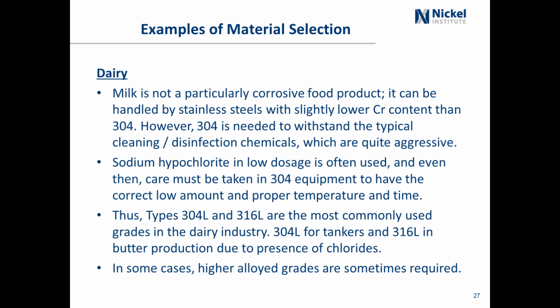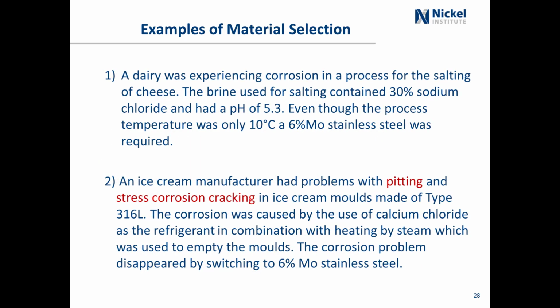Types 304 and 316L are the most commonly used grades in the dairy industry. Like in the case of tankers, 304L could be used, but 316L might be used in butter production because butter can have a lot of salt added to it. Here's some specific examples. A dairy was experiencing corrosion in a process for salting of cheese. The brine used to do the salting contained 30% sodium chloride and had a pH of about 5.3. Even though the temperature was low, only 10 degrees C, they needed a 6% molybdenum superaustenitic stainless steel to prevent pitting in the equipment used for the salting of the cheese.